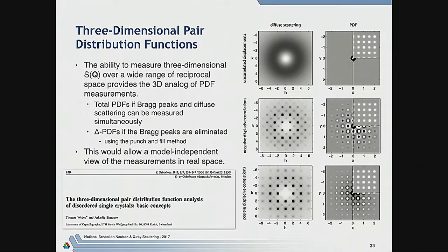Because if you have data in S(Q) in three dimensions in a single crystal, then there's nothing to stop you doing a three-dimensional Fourier transform. And then you have all the distribution of the atomic vectors, but in three dimensions, okay? Which means, for instance, that if the deviation from the average structure involves a transverse displacement, where you have an atom here, and instead of being there in the average structure, it's there, you probably couldn't see that very easily with regular PDF because it would be appearing at the same r distance as the average structure.